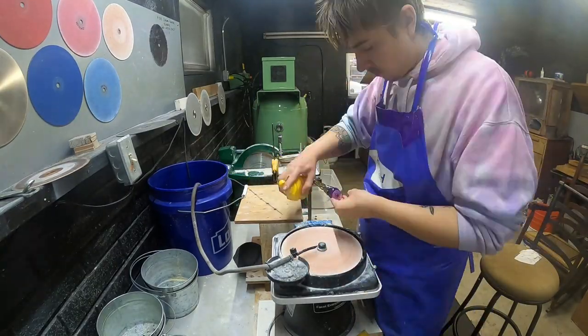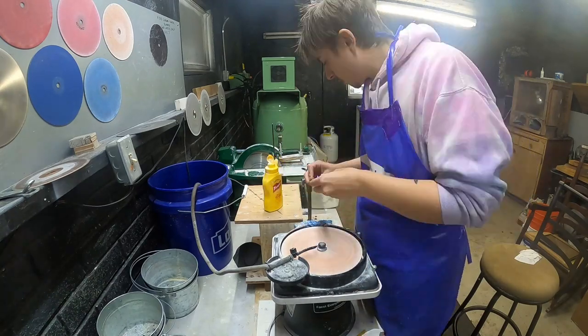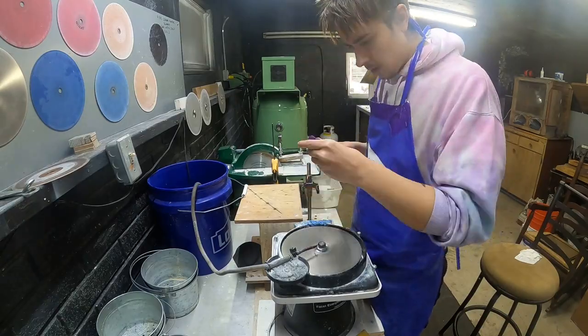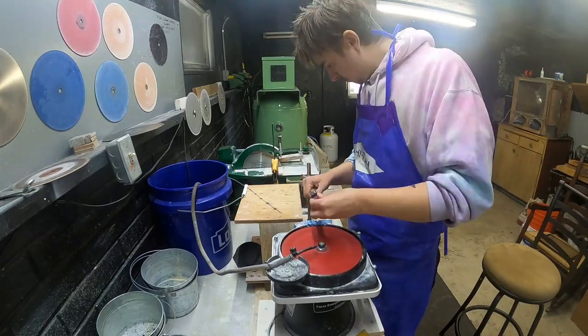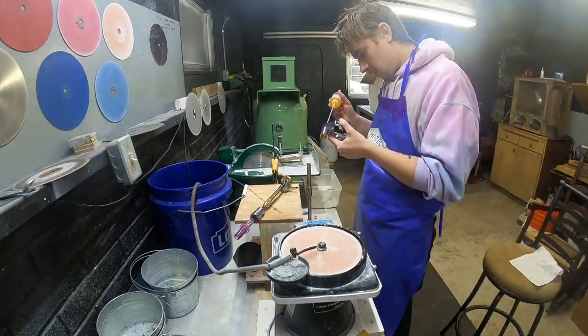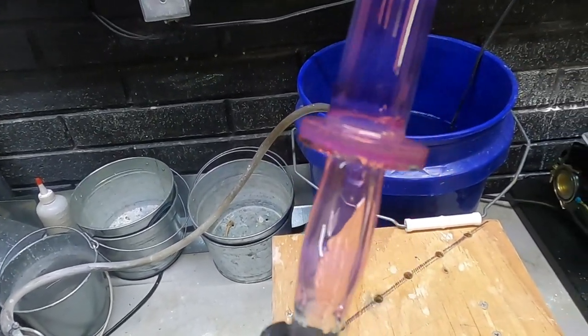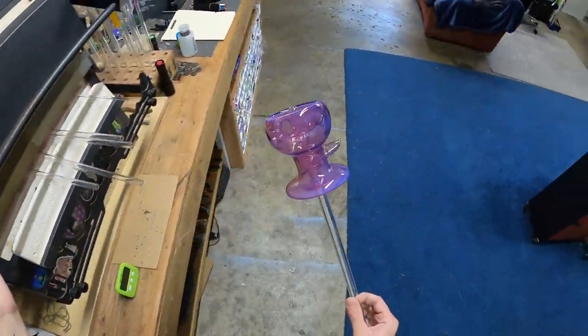After that we'll hit a cerium pad — I use cerium oxide, and that gets all the scratches out and makes it beautifully polished. The cerium step takes a lot longer than any of the others. I use a faceting arm off Amazon, you can find it by just typing in 'faceting arm.' I have a collet chuck attached which can accommodate anything from one millimeter to 13 millimeters, so you can use your 12.7 handles — makes it really really easy. Basically just busting out that mouthpiece, making her all nice and polished.